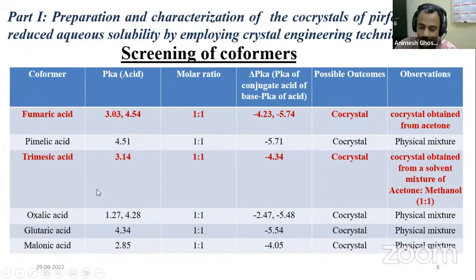So now if we try to discuss the preparation, that means how we have proceeded. The basic fundamental is that if we would like to reduce the saturated solubility of a drug which is highly soluble, we must use a coformer which is less soluble in water. So we have used many carboxylic acids. We have tried fumaric acid, pimelic acid, trimesic acid, oxalic acid, glutaric acid, malonic acid. This is a thumb rule, but that won't always work, right? Fortunately, we got two co-crystals, with fumaric acid and trimesic acid, right?